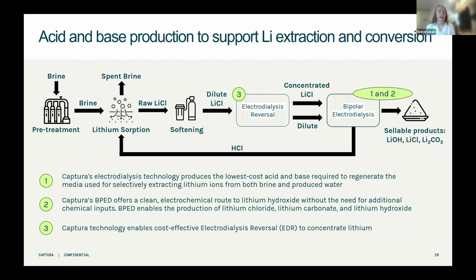We're also looking at how our membranes and stacks can be used in lithium extraction markets. So it's a very complicated and extensive process to extract lithium from brines. And our stacks would just be one component of this, but we believe that it could be a really compelling component considering that these processes need a significant amount of acid and base throughout the process. And we're able to provide that in a fairly cheap fashion.